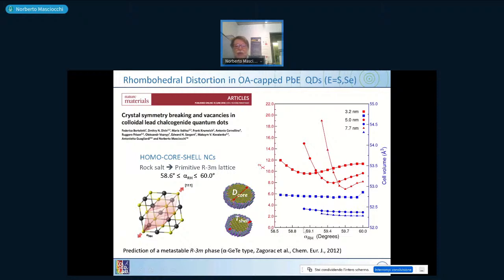Then, by changing still the angle, we also measured the agreement between our data and the model. And this is measured, for example, by the chi-square. This is one of the statistical parameters which can be obtained by the Debye analysis. You can see that all these curves, despite having the same constant cell, have a minimum. The larger minimum is for the larger particles, very easily visible, but with a value which is close to 60 degrees. And remember, 60 degrees means, in this kind of deformation, ideal cubic.